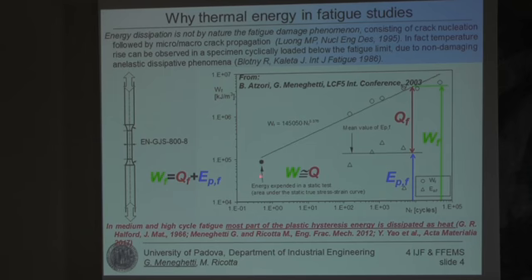You see that the total mechanical energy is an increasing function of the number of cycles to failure, but this is not a new result. It had been found many years before, in 1966, by Halford, who performed such kind of tests, and we simply found nicely the same slope of such a curve, about 0.33, that Halford found in 1966.